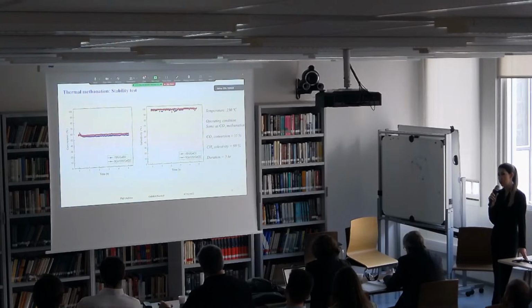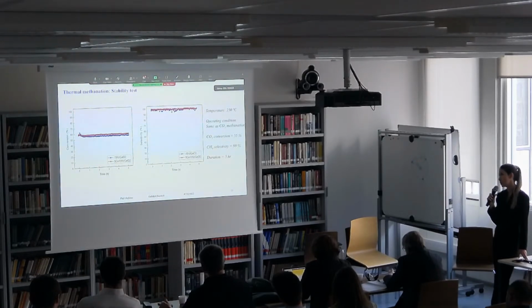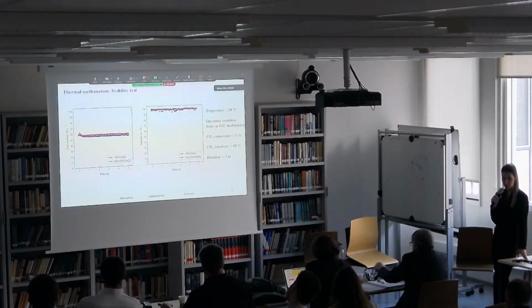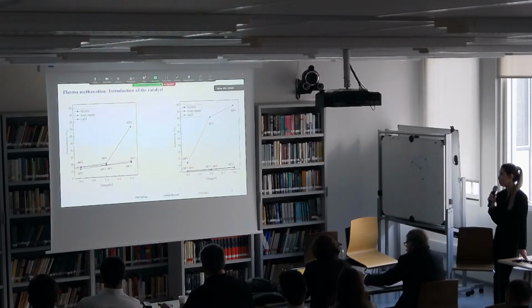Also, in order to study the stability of the catalyst, the stability test was held under thermal conditions at 250 degrees for 5 hours with the same conditions as methanation. As you can see, in the first 20 minutes the CO2 conversion slightly decreased, but until the end of the test, the conversion and selectivity remained the same, showing that the catalyst was stable under thermal conditions.